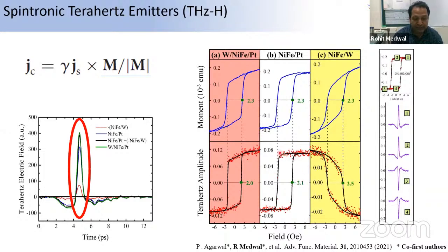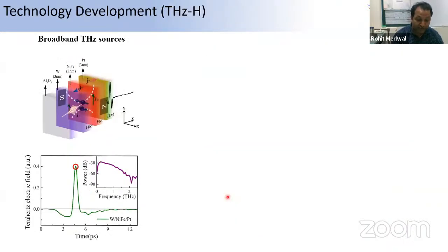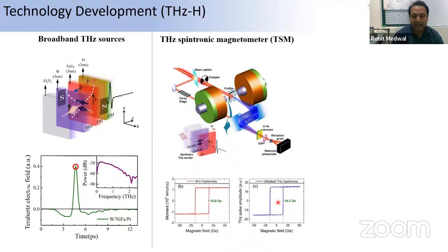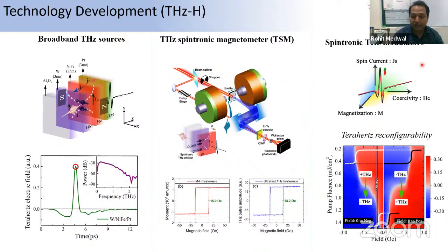And using this discovery, we have clearly shown that we are able to design this spintronics magnetometer, which is a really broadband terahertz source, and also a spintronics terahertz modulator, where we can control the coercive field, magnetization, and then spin current by the intensity of the laser, by the heating effect, or by several means. I'm going to talk about how we can design these new spintronics emitters in the next slide.